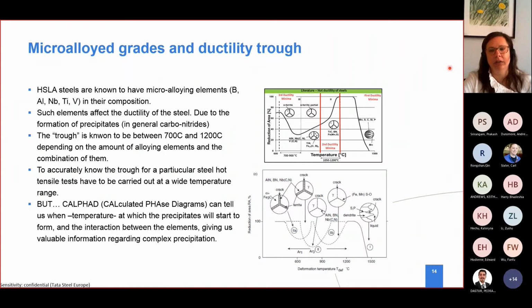And it is very well known that even though they are beneficial, because we add them to the composition to improve the final properties of a product, not for nothing, however, you have some disadvantages: during processing, they are known to have a ductility trough. I explained before that the first ductility trough happens at the semi-solid region. But then while cooling, you have a second and sometimes a third ductility trough, or even an overlapping of several ductility troughs, depending on the precipitation, depending on all the processing and all the phase transformations that are happening due to the chemical composition.